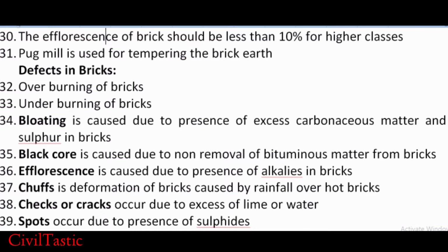Bloating is caused due to presence of excess carbonaceous matter and sulfur in bricks. Black core is caused due to non-removal of bituminous matter from bricks. Efflorescence is caused due to presence of alkalis in bricks. Chuffs is the deformation of bricks caused by rainfall over hot bricks. Checks or cracks occur due to excess of lime or water.